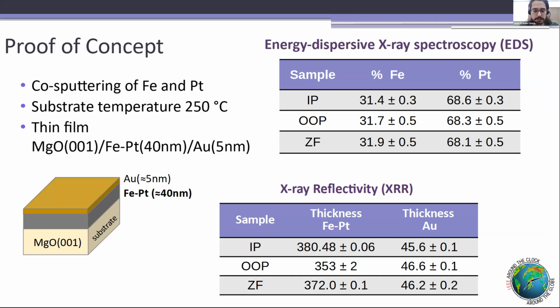And since we observed some disturbance in the plasma inside the chamber, we did measurements of EDS and X-ray reflectivity to see if in each site of the deposition plate we would have the same amount of iron and platinum, and whether the thickness of the film was affected by the field. So from the energy dispersive measurement, you can see that we have the same amount of iron and platinum in this co-sputtering deposition in all the sample positions.